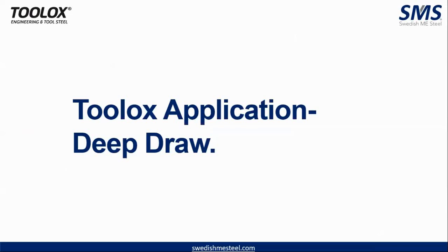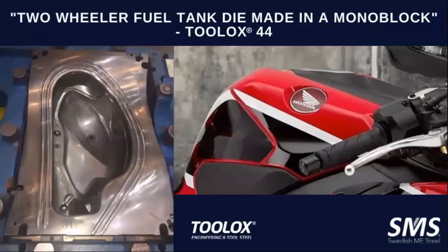So let's see a couple of applications in deep draw. This is a tool that we did for Honda. This single piece is 1 ton. As you all know, this is for a two-wheeler fuel tank. We have scooped out 500 kgs of material from it. No stress relieving after machining. We have done nitriding at 550 degrees centigrade. No problem in distortion. We are able to match it.